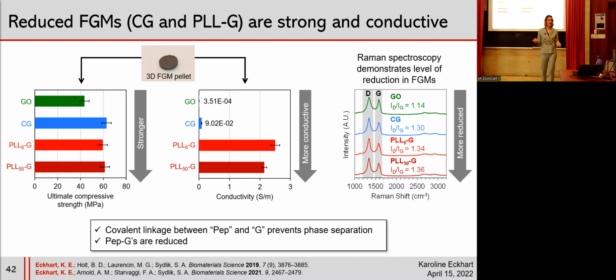And the second reasoning behind this result is likely due to the level of reduction. So over here on the right, we're looking at the Raman spectroscopy of each of the FGMs. And Raman is a technique that researchers commonly use to evaluate the level of reduction of a graphenic material by comparing the D band to the G band and their intensities. So here, a higher intensity of the D to G band indicates a more reduced material, and a more reduced material is generally more conductive and more mechanically strong.